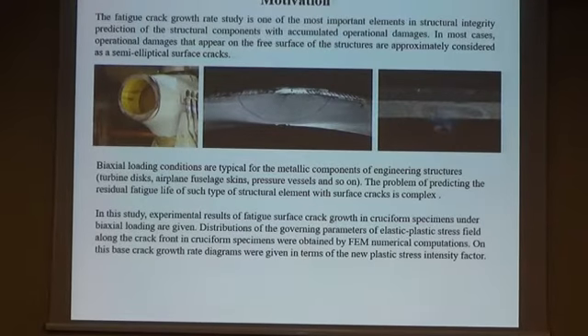Some words about motivation. Fatigue crack growth rate study is one of the most important elements in structural integrity prediction for structural components with accumulated operational damage. In most cases, operational damage that appears on the free surface of structures is approximately considered as a semi-elliptical surface crack. And biaxial loading conditions are typical for the metallic components of engineering structures, such as turbine disc, airplane fuselage skins, pressure vessels, and so on. So the problem of predicting the residual fatigue life of such type of structural elements is complex, and the actuality of this problem is evident.